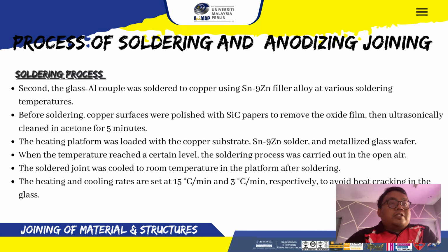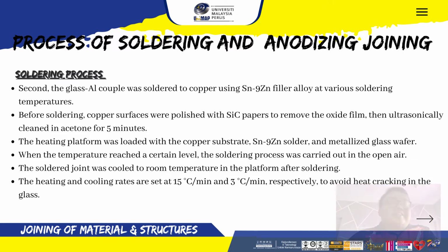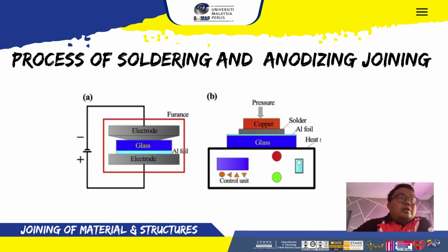When the temperature reached a certain level, the soldering process was carried out in the open air. The solder joint was cooled to room temperature on the platform after soldering. The heating and cooling rates were set at 15 degrees Celsius per minute and 3 degrees Celsius per minute, respectively, to avoid cracking in the glass. Okay, this is the process of soldering and anodic bonding of metal to glass.